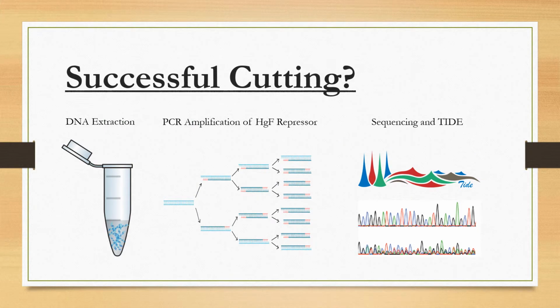Having observed that the nanoparticles were taken up by the cells, our next step was to see if the precise cut at the fetal hemoglobin gene site had been made. In order to do this, we extracted the DNA from our cell samples and amplified a portion of the fetal hemoglobin gene repressor sequence using PCR. We then analyzed the sequences using TIDE software, looking for a precise and clean cut at the desired location.